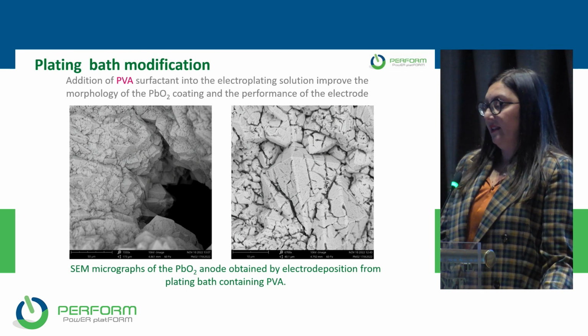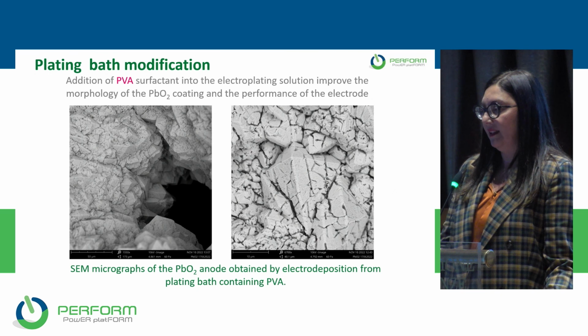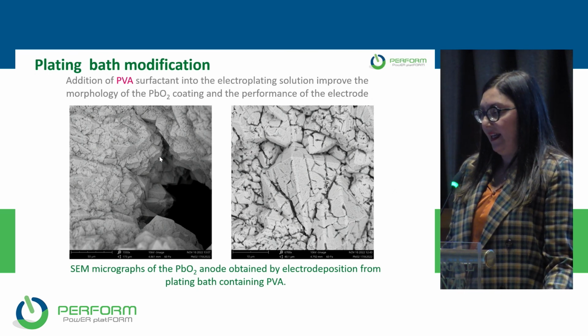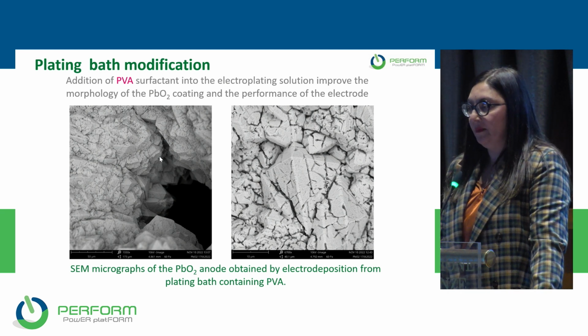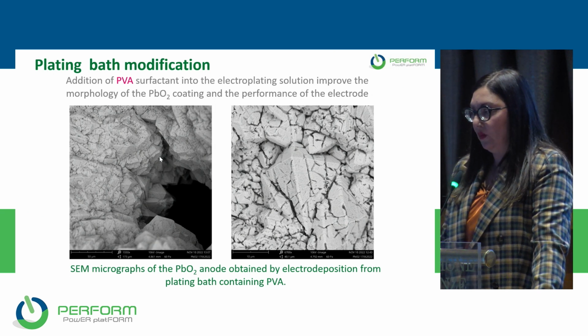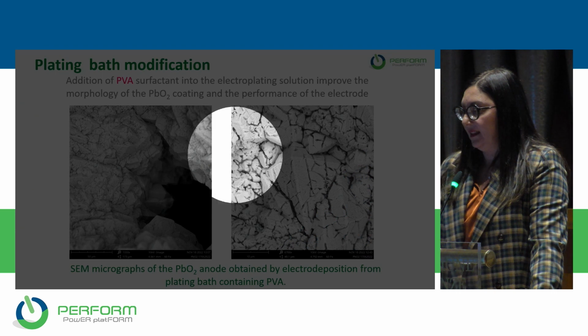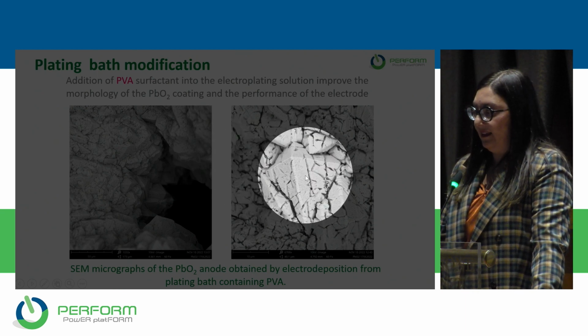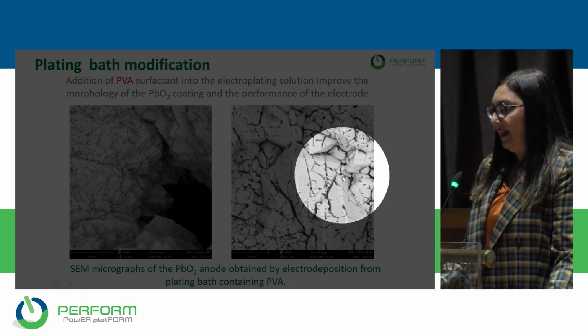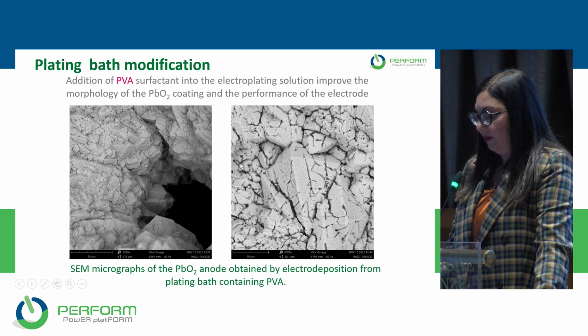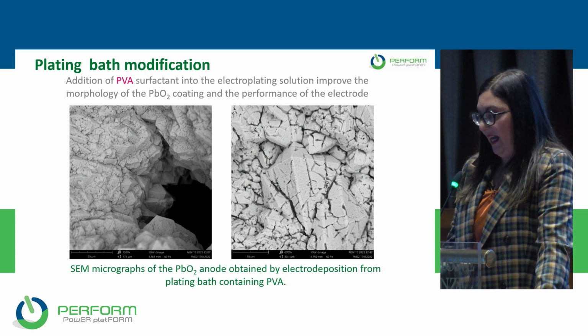Another improvement that we obtained was modifying the plating bath by adding PVA, a surfactant, in the electroplating solution. And what we obtained was this type of material, in which the morphology is better than the current electrochemical lead dioxide system, because it has a larger surface area and small grain size, and these characteristics are interesting because they confer to the electrode a longer lifetime.